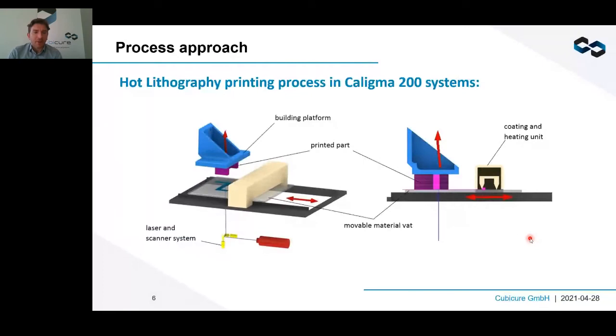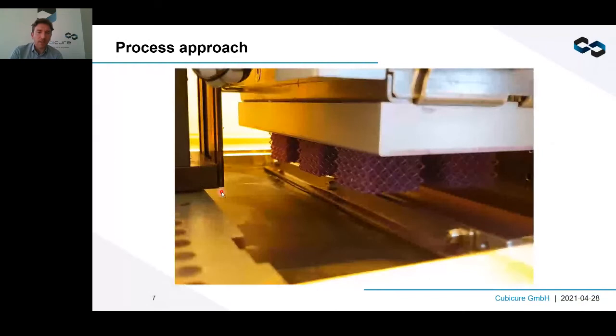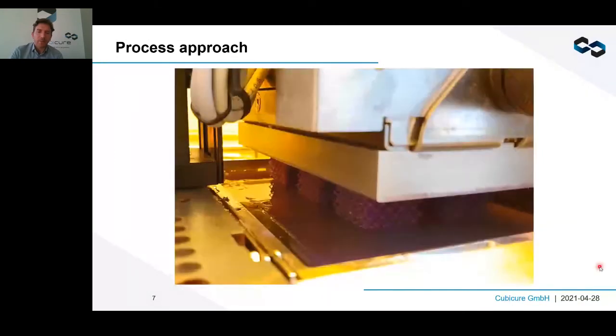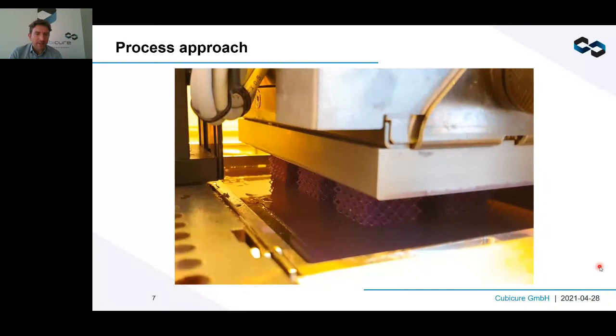Here you see a short schematic how this is done in a Caligma machine. So this can be done in different ways, but this is how it's done in a Caligma machine. So you have a material vat, which is indicated here in the glass plane. In our case, the light information comes from below. You see it on the left side. In our case, most often it's a laser scanning system. And so we provide a thin layer of photoresin, and then it gets exposed with the layer by layer information. I hope that video is running smoothly, at least that you can see what is going on.